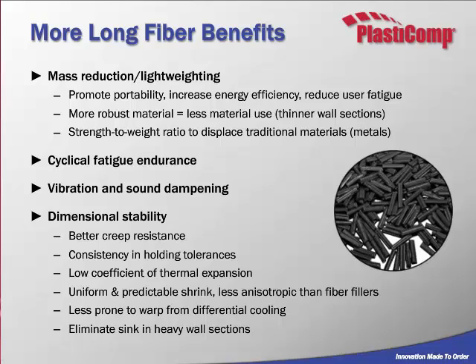So when we look at the benefits of long fiber over short fiber in particular, one of the benefits with impact strength is that you're able to thin out the walls. So if you've got a certain component with a short glass part and the walls are thick and you're looking to reduce the thickness to lightweight that material, long fiber may be the answer because of that increased impact strength you'll get, especially in thin-walled parts.